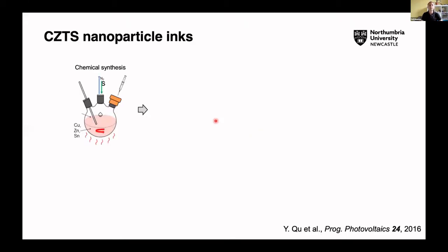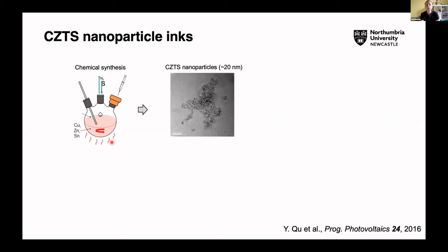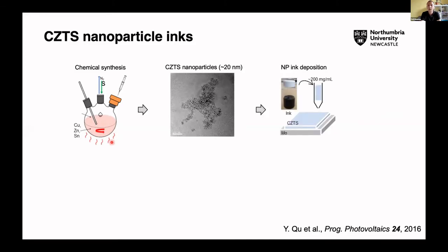So the manufacturing part first. This is how we make our copper zinc tin sulfide nanoparticle ink. We inject metallic precursors into a hot surfactant, which is OLA, and we do the reaction at around 250 centigrade for around half an hour, and we're able to nucleate these nanoparticles, which have the Kesterite phase. Interestingly, for this fabrication process, that phase, that crystal structure, is preserved throughout the fabrication process, and that's different to co-evaporation or sputtered Kesterite solar cells, or indeed CIGS as well.